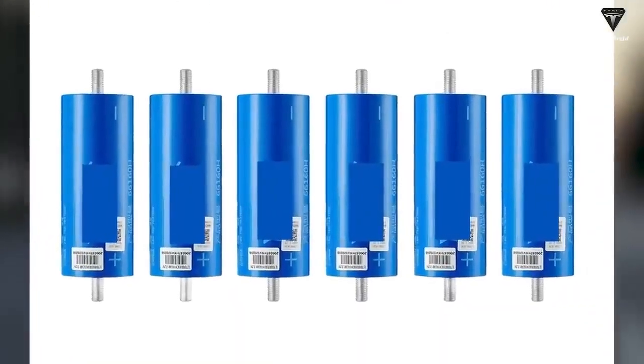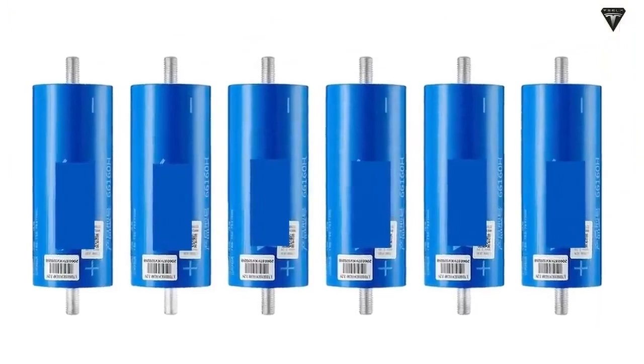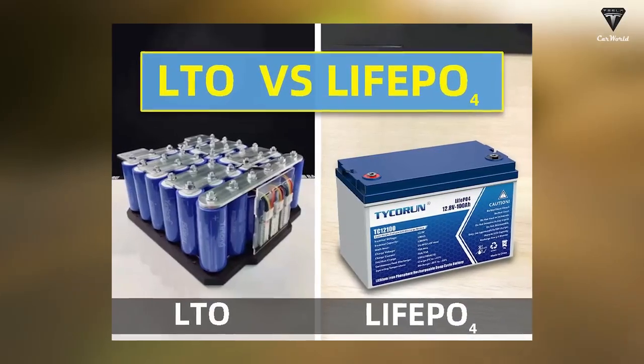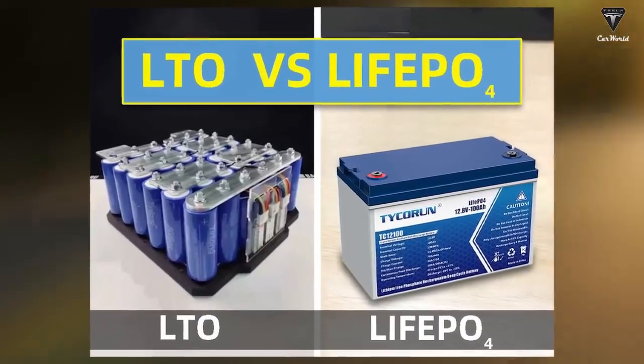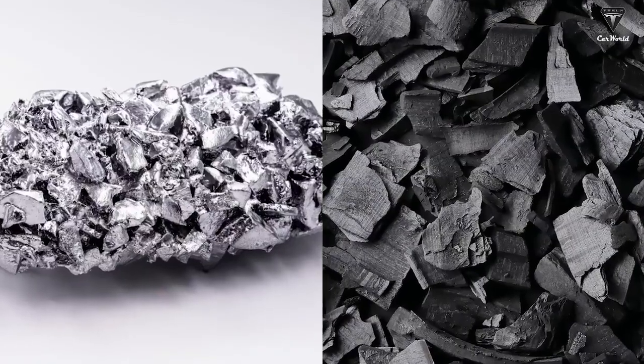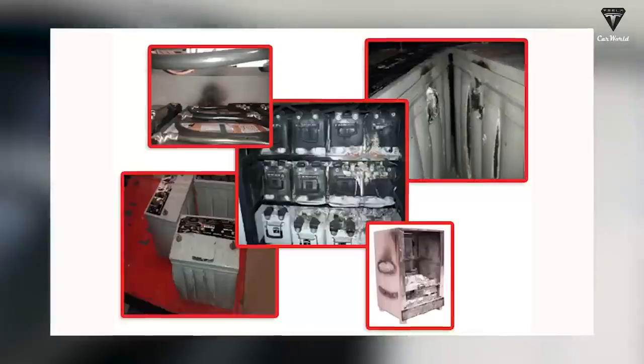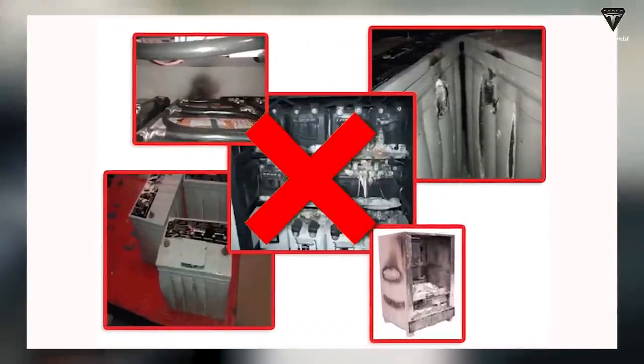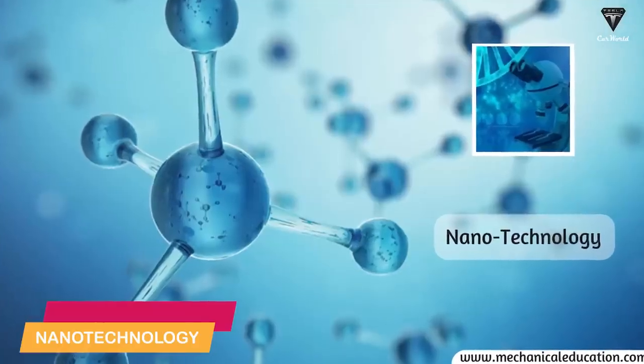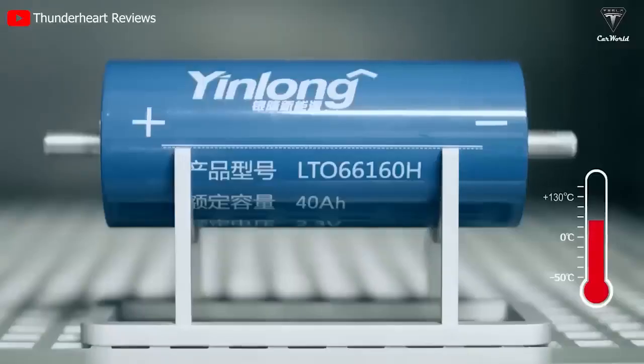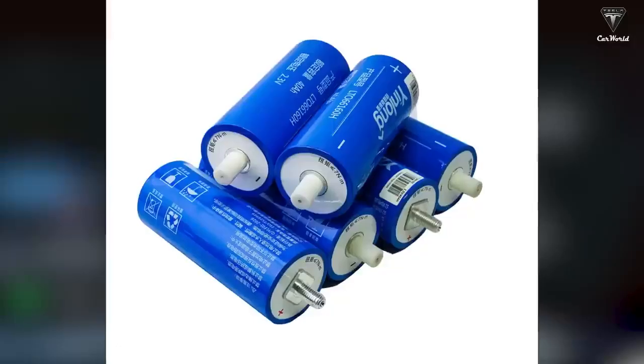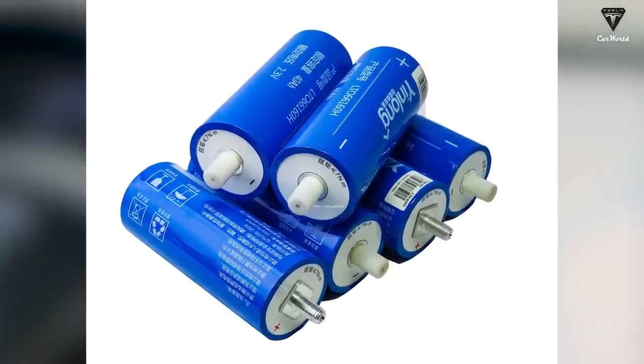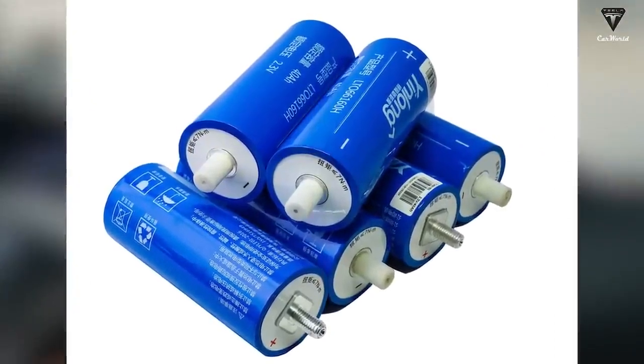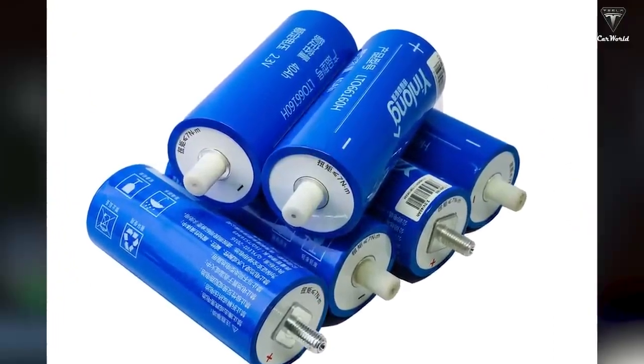Furthermore, in terms of LTO battery safety, the higher level of safety compared to LFP batteries is due to this technology's lower operating voltage. Because titanate batteries are carbon-free, they avoid thermal runaway or overheating, which is the leading cause of fires in traditional energy storage. Because of the nanotechnology used, the low temperature performance of LTO batteries can achieve up to 80% of the full charge capacity at minus 30 degrees centigrade.